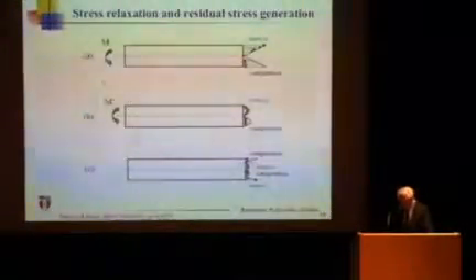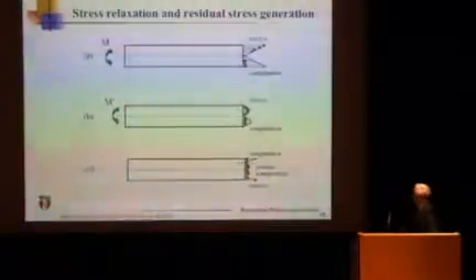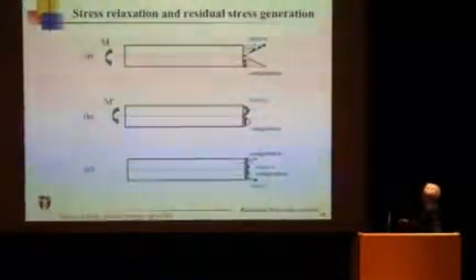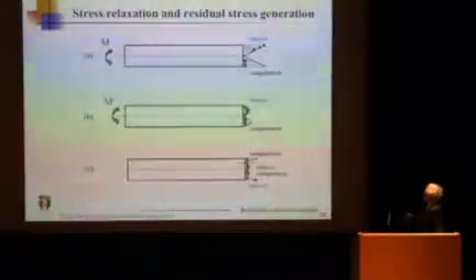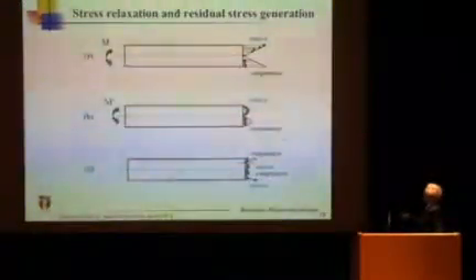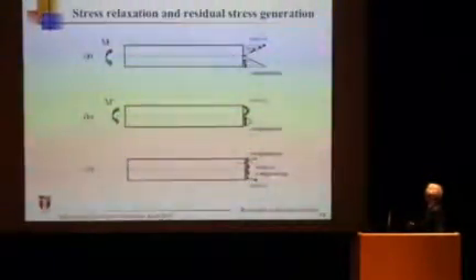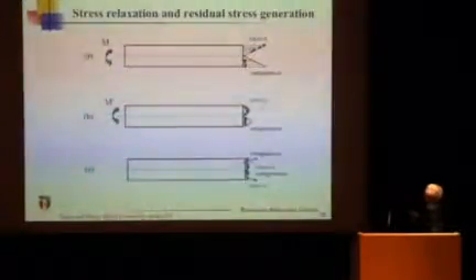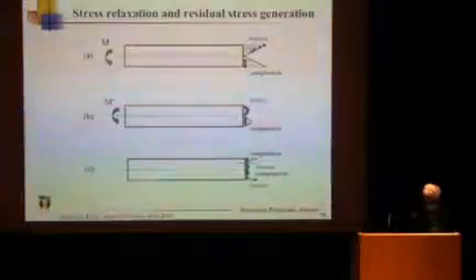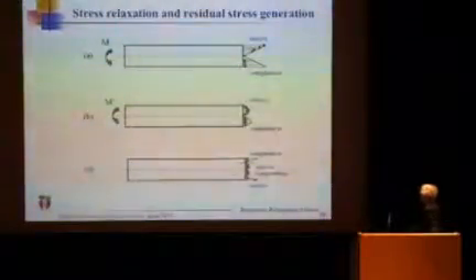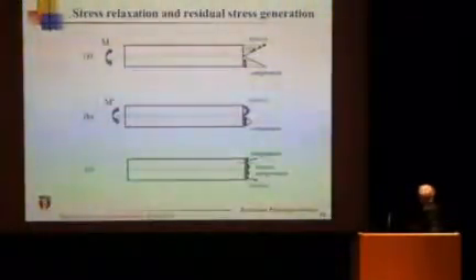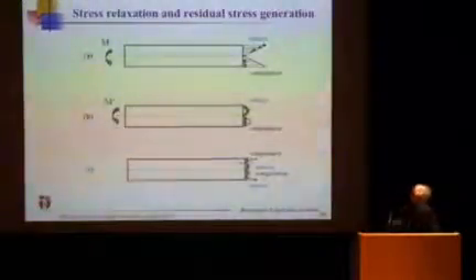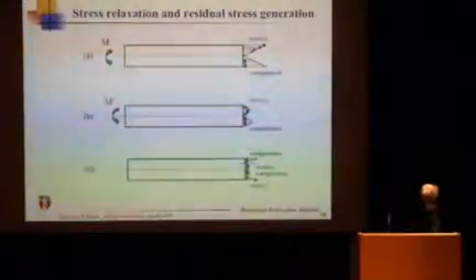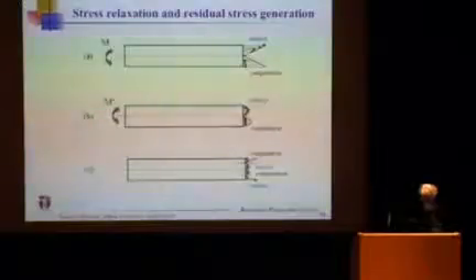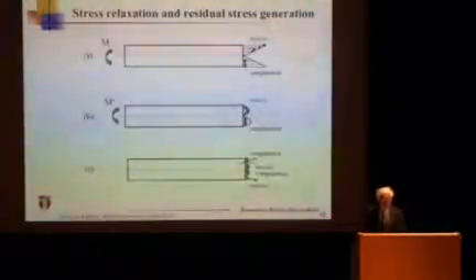One of my postdocs who had a mechanical engineering PhD explained to me this way: if you have a bending stress, you have tension and compression uniformly changing across the fiber. When you have surface relaxation, surface tension and surface compression are a little bit lost, and when you let go, you end up with this funny stress profile. Where the tension was, compression is formed. Where compression was, tension is formed.